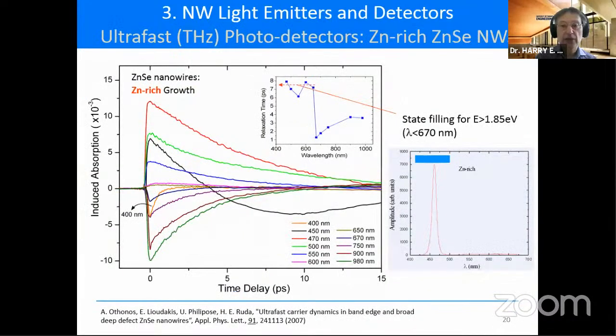The last part of this optoelectronics section is a couple of things I want to talk about, starting with time response. If we look here, we've done terahertz based spectroscopy, and we can look at the defect based band, and we can tune that to get picosecond response very nicely from these structures. We did that both for the selenium rich and also for the zinc rich, where it's just a state band filling controlling the lifetime. So this whole idea is about tuning the structure to tune the response.